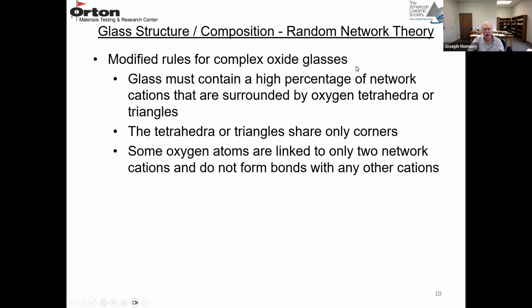If the glass is more complex, if there's glass modifiers or glass intermediates, the glass must contain a high percentage of network cations that are surrounded by the oxygen tetrahedra or the oxygen triangles. Again, the tetrahedra or triangles only share corners. And now some of the oxygen atoms are linked to only two network cations and do not form bonds with any other cations. So that's where the non-bridging oxygens come from.